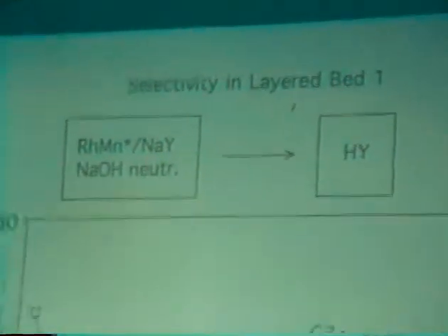You can think of two conceivable hypotheses. The trivial one is that protons are active sites in their own right and convert the primary oxygenates to other less attractive things. So we did layered bed experiments. We used the neutralized catalyst — which we know does a good job — and behind it downstream, a proton-containing catalyst, which is HY zeolite. And indeed, for a long time absolutely no oxygenates are formed. After a long time a few appear, so these protons apparently destroy, in secondary reactions, the primary oxygenates, and finally when the protons are presumably neutralized, some oxygenates come through.